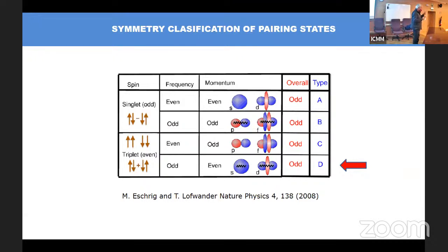S wave is an even function in the orbital sector. Triplets are even under the exchange of the spins. So for the wave function to be odd, it has to be an odd function of the energy, or odd frequency, which essentially means, if you want things in the time domain, that electrons with the same spin of the pair will avoid being at the same position at the same time, right? To comply with the Pauli exclusion principle.